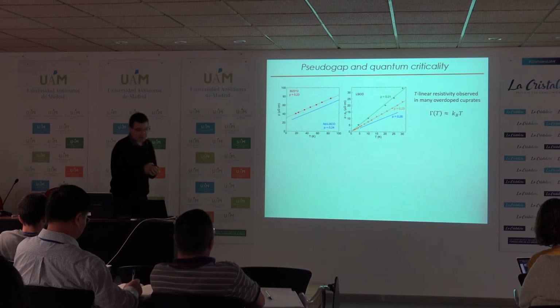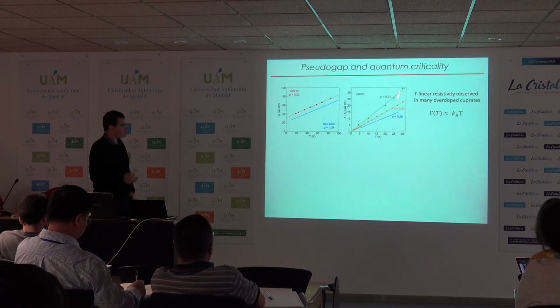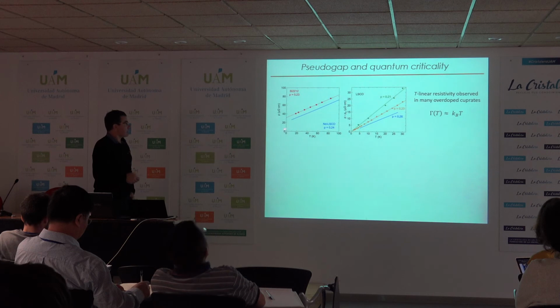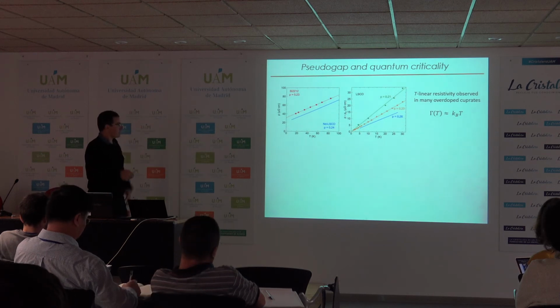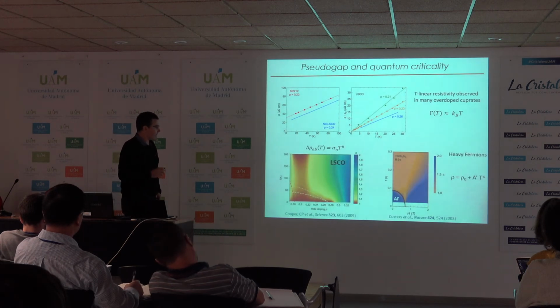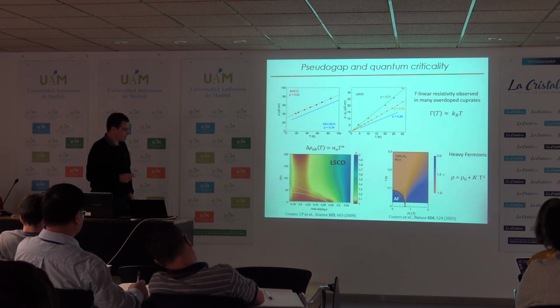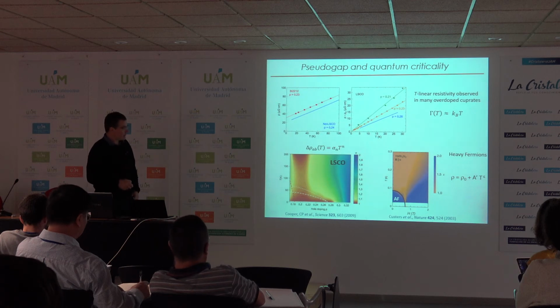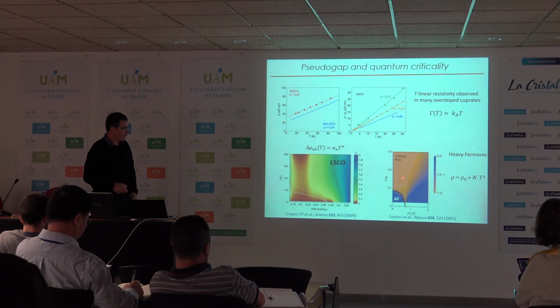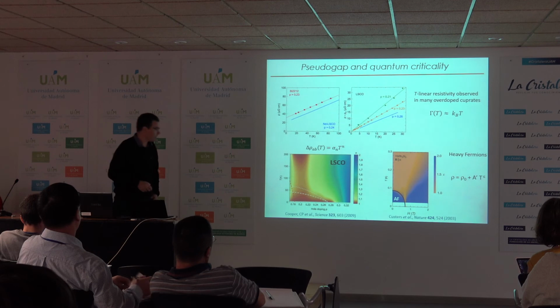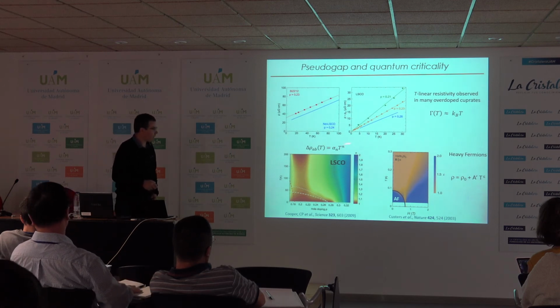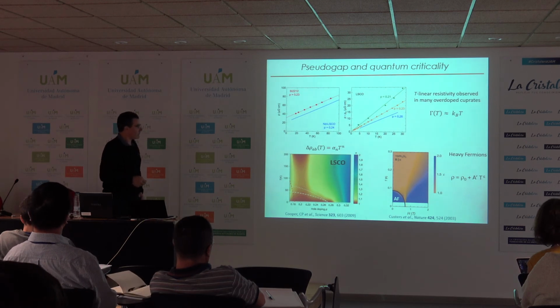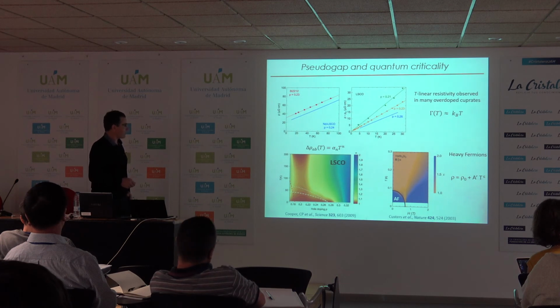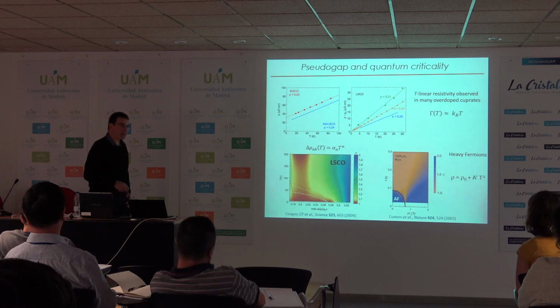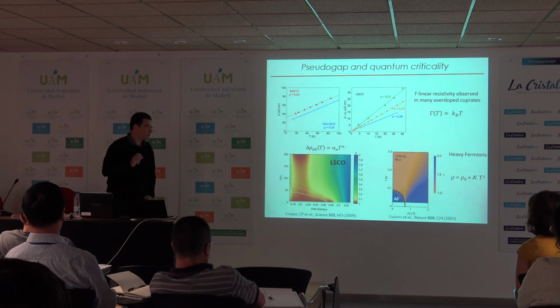I showed you before the T-linear resistivity of different overdoped compounds, with the scattering rate given by Planckian dissipation. As in the archetypal quantum critical system, the resistivity is linear, but in a way that we called, 10 years ago, anomalous quantum criticality. In the heavy fermion systems I showed you before, the resistivity remains linear down to very low temperature only at the quantum critical point. Whereas in LSCO, here I show you again a map of the exponent of the temperature dependence of the resistivity. In red, this is 1. In blue, this is 2. And you see that the resistivity remains linear over a broad range of doping at low temperature.